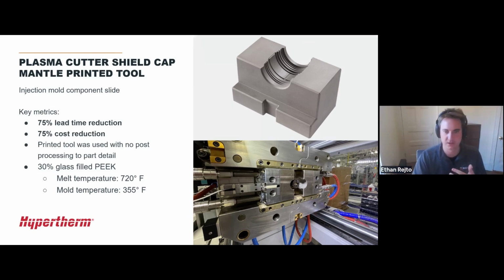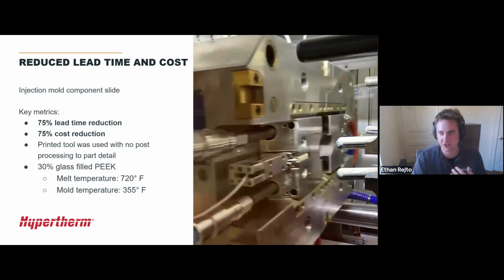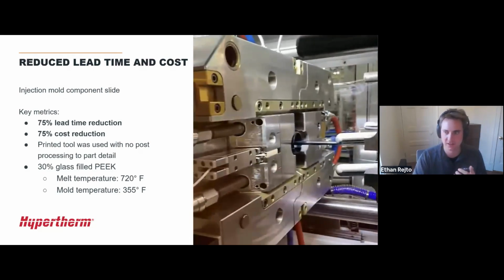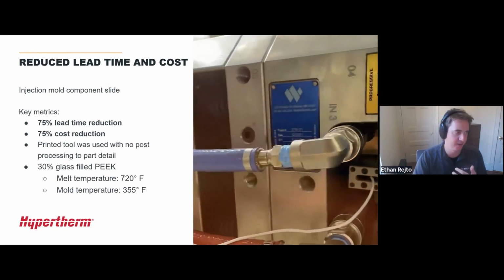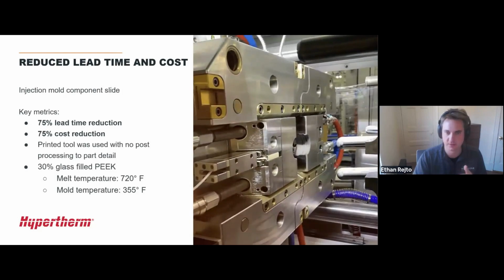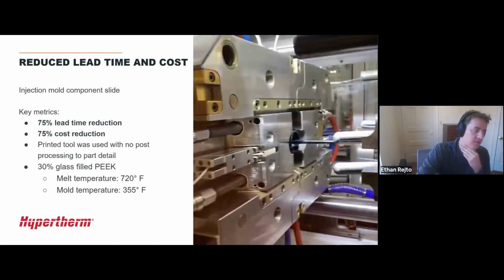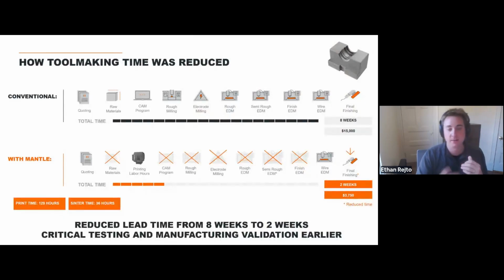And they were running that 30% glass-filled PEEK, so that high temperature, highly abrasive engineering resin, with no real challenges here. You can see it actually being run here. You can watch videos like this all day, but you can see no challenges. And they produced a couple thousand of these parts, I believe, with no challenges. So all in all, what did that mean? It meant they reduced the lead time on this from 8 weeks down to 2 weeks. And you can imagine how significant that 6 weeks, month and a half of time savings is when they're trying to validate this design, move to production, and get this design on the shelves, on the market, and being sold.